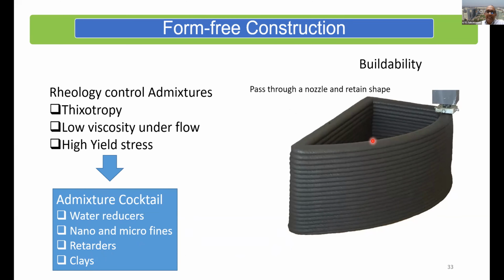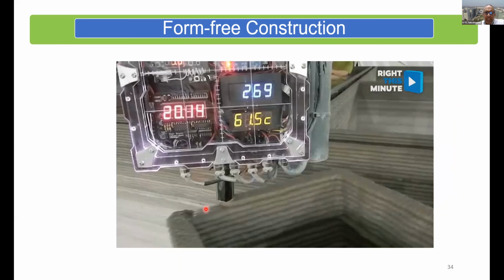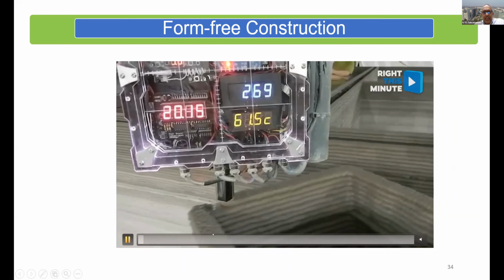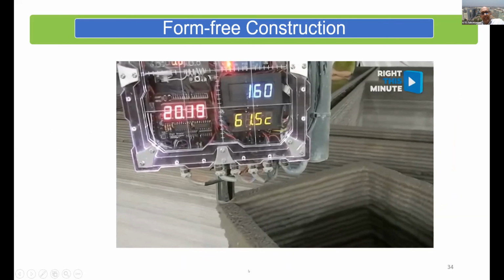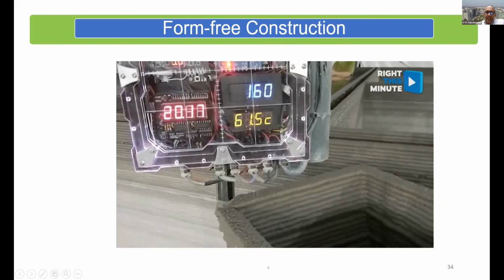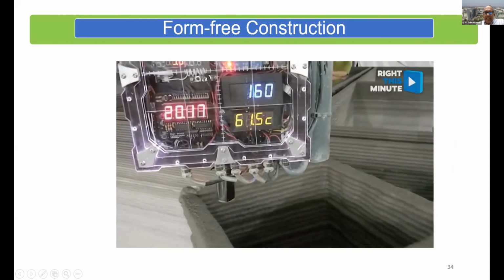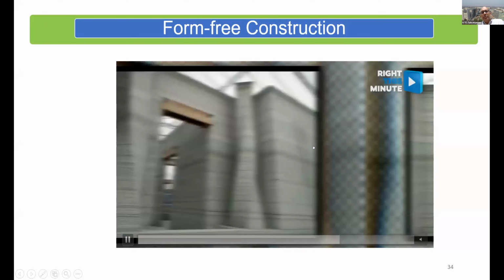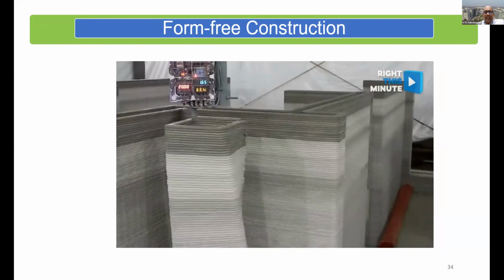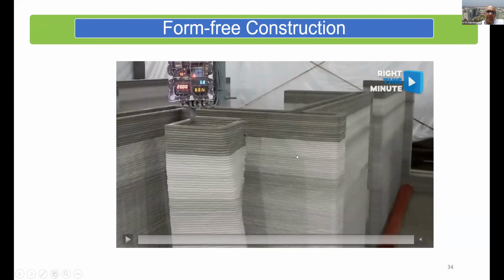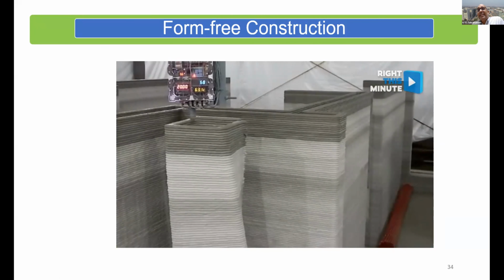Now with this, essentially, I can assemble a whole structure layer by layer. And this is just to demonstrate how a structure would be built. If the video would play, you would see that a 3D printed concrete structure is essentially assembled one layer at a time. And you can see all the multiple layers as they're being stacked up. This is how the layers have been stacked up. And now you can do form-free construction. You're not limited to rectilinear shapes. And the entire structure is assembled layer by layer. But of course, there are challenges here, is that we're still learning how to integrate reinforcement into this concrete. So that is an active area of research, which will basically, once we solve that riddle, then we should be able to 3D print structures of the future.